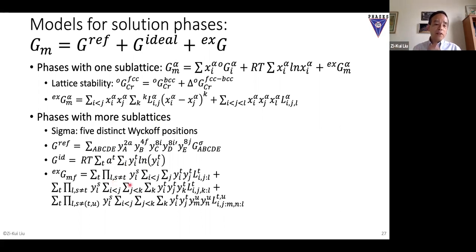So that's why sigma phase has always been modeled by 3 sublattices instead of 5 sublattices - it becomes too complicated. You have no data because when you experiment, it measures the combination, it doesn't measure individual sublattices. And so until DFT calculation becomes available, we can't do complex systems. And again, that's your database for the iron chromium.